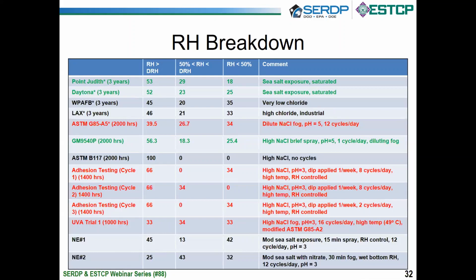So for these outdoor samples, you can see that they're between 40 and 50% relative humidity. And you can see the times above the deliquescence point. Sorry, this is the percentage of time above deliquescence, and this is the percentage of the time in that sub-deliquescence but corrosion regime, so above 50%, and then this is below. And what we can do is start comparing these to what you see in the rest of these.